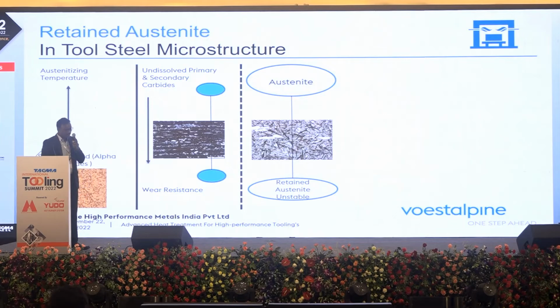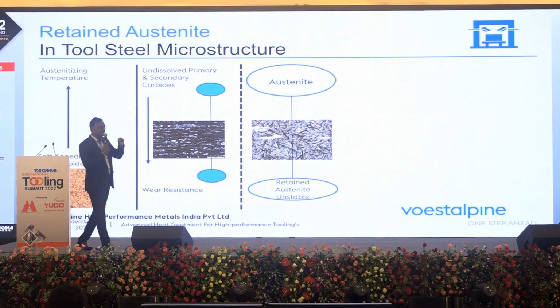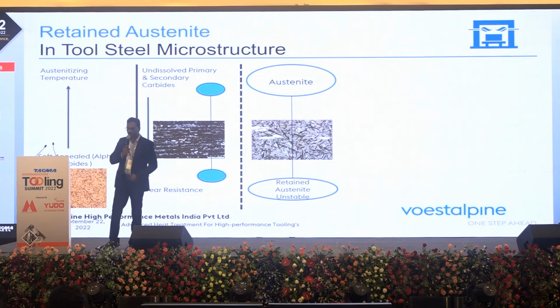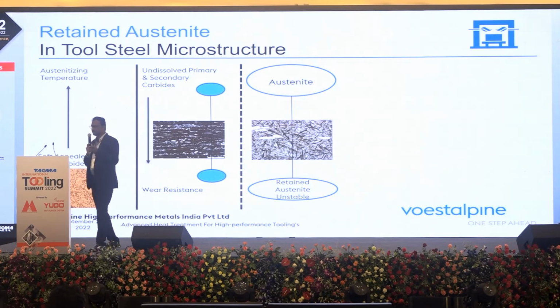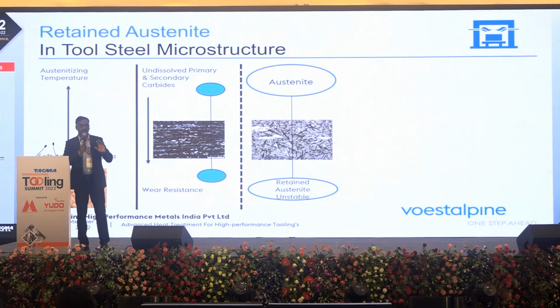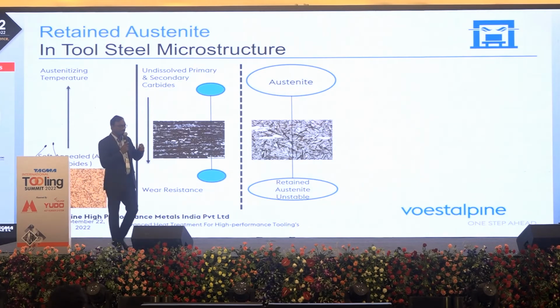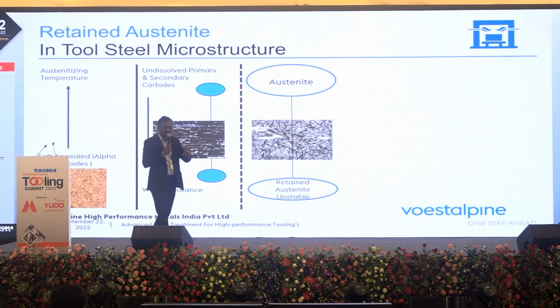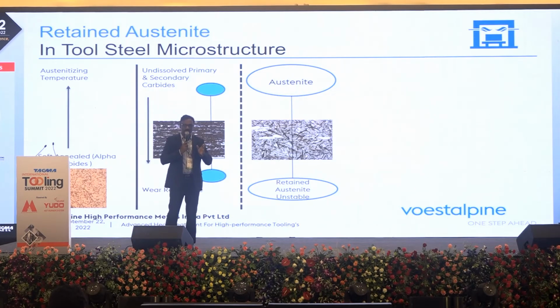So the completion of the transformation from austenite to martensite will never take place at room temperature for most cold work tool steels and high-speed steels. There is certain content which is detrimental for your application that stays back, and that is called retained austenite. Now, if you want to improve the performance by 15-20% with the same effort you put into tool manufacturing, you need to convert this retained austenite into a complete martensitic structure. There is a limitation.